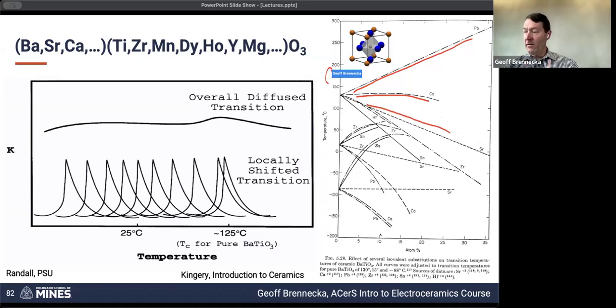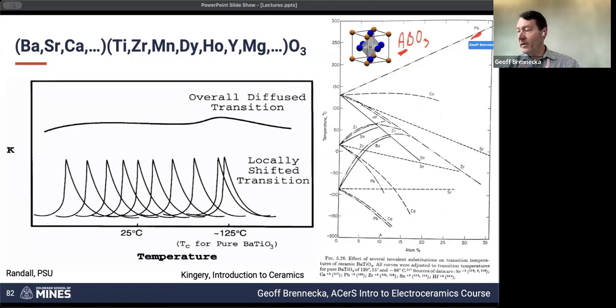So this is the order from low to high temperature, just like we saw on the last plot. And you'll notice, if you look closely, that if this is barium titanate, ABO3, the alloying elements or the dopants that we're putting on the A site, so this is lead replacing barium, calcium replacing barium, strontium replacing barium, those cause shifts in these temperatures. If we look at the materials that are going on the B site, so that's these guys, the B site right there. So that's zirconium.